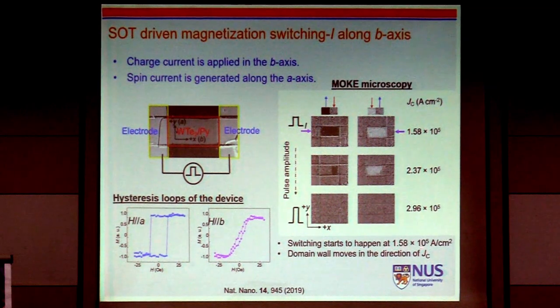So the switching current is 1.5 times 10 to the 5th, which is about 4 times smaller than that of the topological insulator. But once we calculate the power consumption, because of the small resistivity, the total power consumption drops about one order compared to the topological insulator case. Anyhow, this material is very interesting.